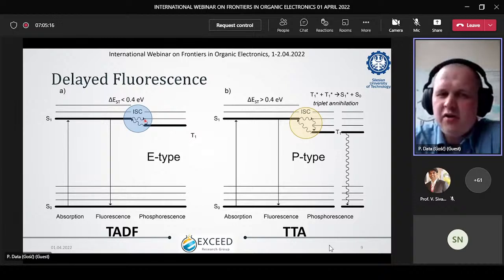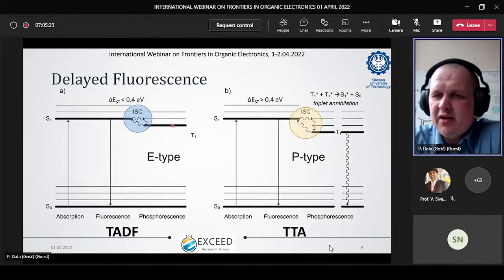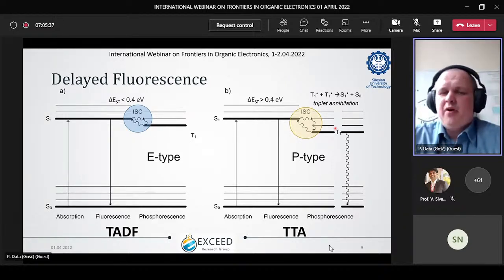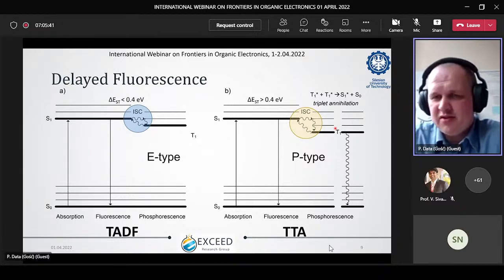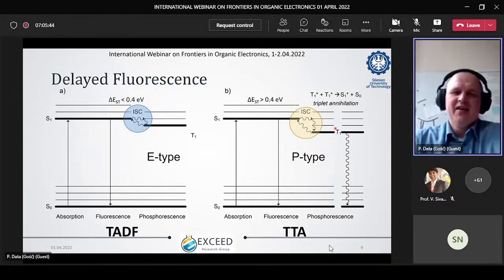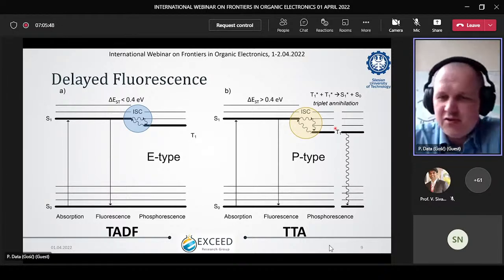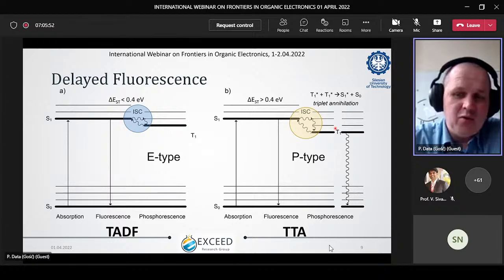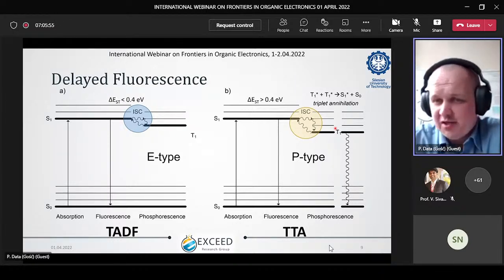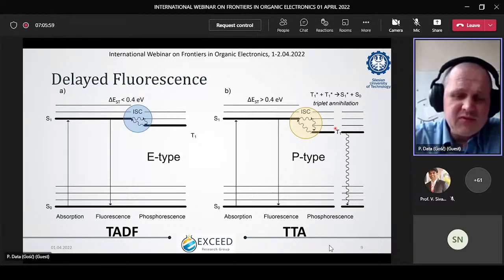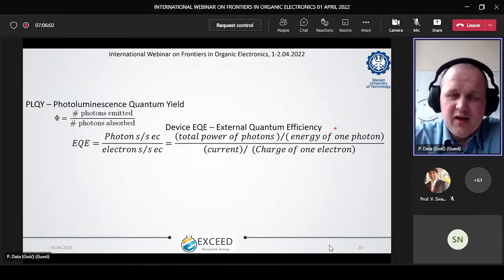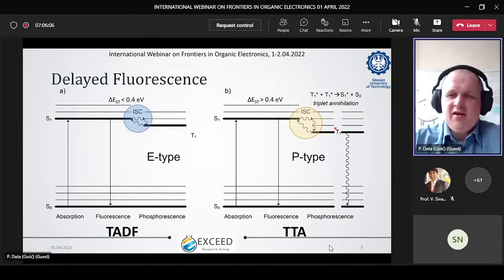In the TADF, we are harvesting 100% of the triplet state, those excitons are pushed to the singlet. And in the case of TTA or P-type delayed fluorescence, we can only harvest 50% of our triplet state. So if you think about the 25 to 75 ratio, in the case of P-type, we are harvesting only 50% of the 75% of excited states, which means in all cases we are pushing for the TADF process rather than TTA. Nevertheless, in many molecules, it's a mix of the processes, E-type and P-type, and that's why we always need to investigate that. So we know what the mechanisms are, but we need to investigate.